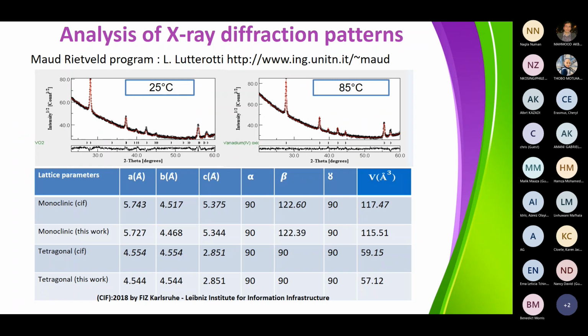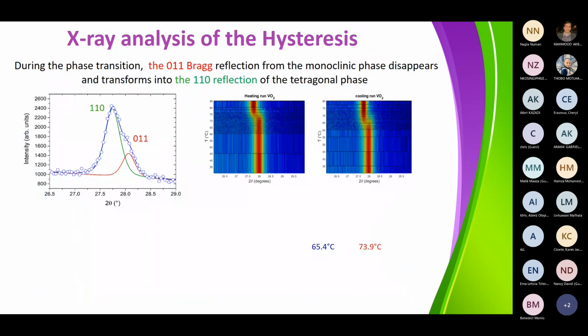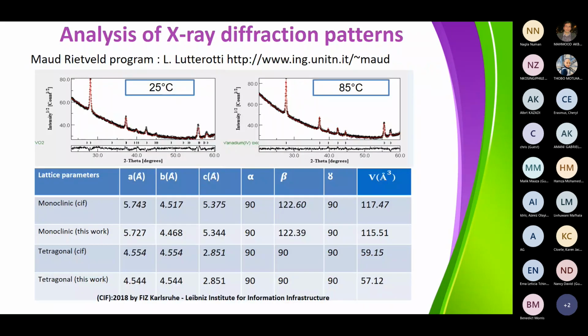And we can calculate, and you can see that there is not a big difference between the calculated lattice parameters that we made with our fits and the one from the CIF file. Fortunately. Otherwise, we could say that there was a problem, but this is the type of information that you can get.